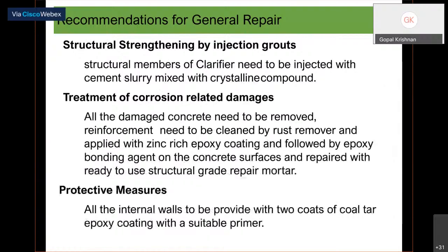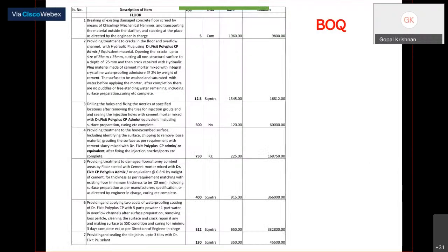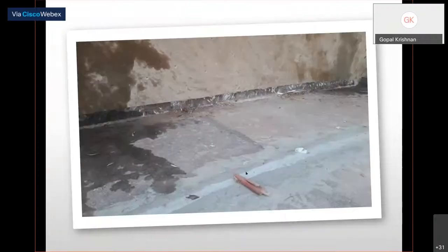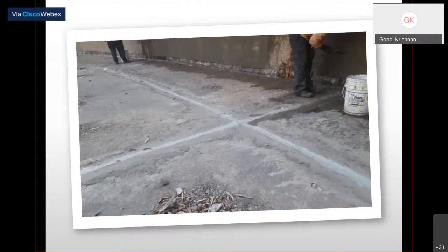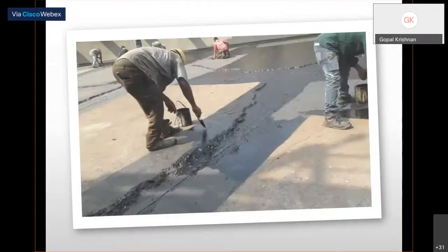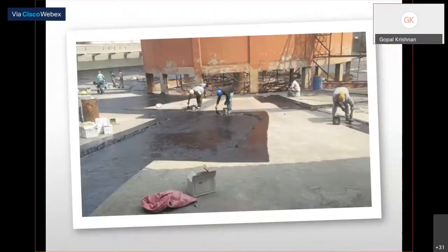So we gave the complete solution, and finally we recommended epoxy based anti-corrosive treatment wherever the corrosion happened, and we provided coal tar epoxy coating to protect the repaired surface. So this is a BOQ. Item-wise, we give rate analysis so that the customer can take it further. This is a stage-wise photograph. You can see how the repair was carried out on all the 24 joints, and the epoxy coating has been done as a protection measure.